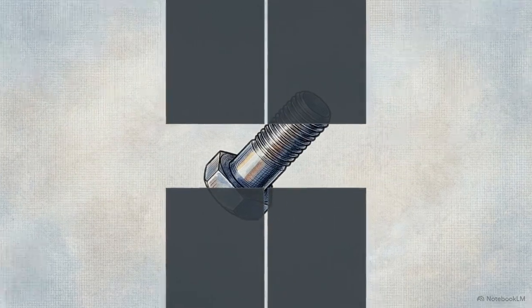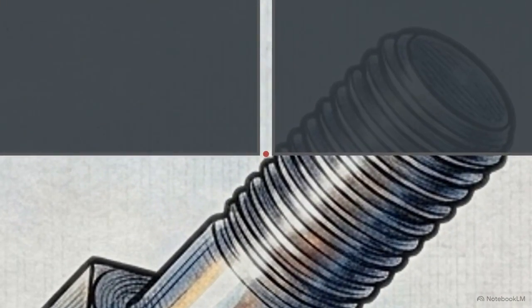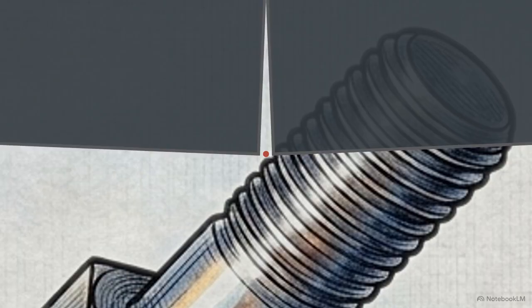When the bolt is inserted and clamped down, the glowing red marker indicates that the highest point of stress aligns perfectly flush with the microscopic gap between the two flange faces. Positioning a stress riser exactly at the joint interface is highly volatile. If the flange faces separate even slightly on one side, they act as a fulcrum. The mechanical bending force focuses entirely onto that singular geometric point at the runout.